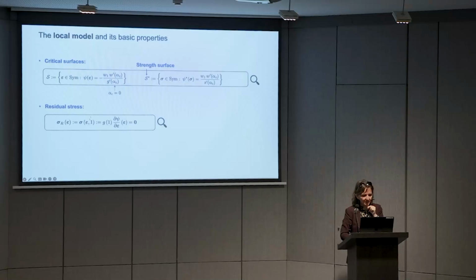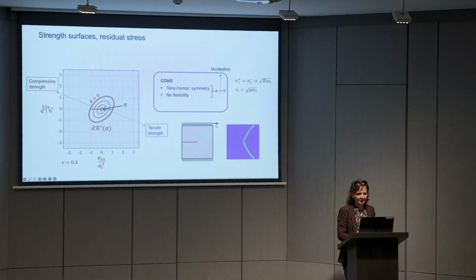So this is a bit the crack-like behavior I was mentioning before in the block example. And for that, the important thing is the residual stress. The stress that you obtain when alpha is equal to 1, which means complete damage. And in the standard model that we're looking at, this is 0, yeah, because we are still degrading the entire elastic strain energy density, and this is the source of the trouble with the contact conditions. But this is really the very basic for now, so we are still in this setup.